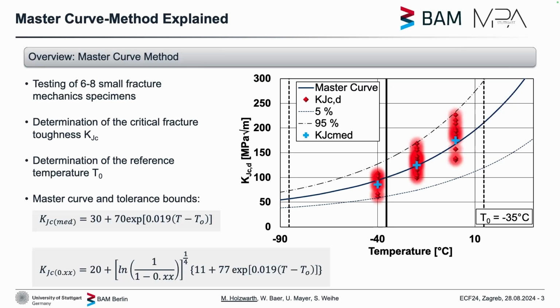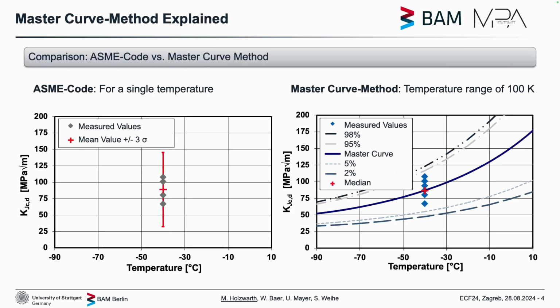And what's so good about it? Well, if we check it, for example, with the method in the ASME code, we only do 4 tests, but in the end, we only get a single value for the fracture toughness. And in the master curve, we only have to do 2 more tests, 6 in total. And we get this whole temperature range from -90 to +10 degrees, for example. So with just 2 more tests, we get a whole lot more to work with.